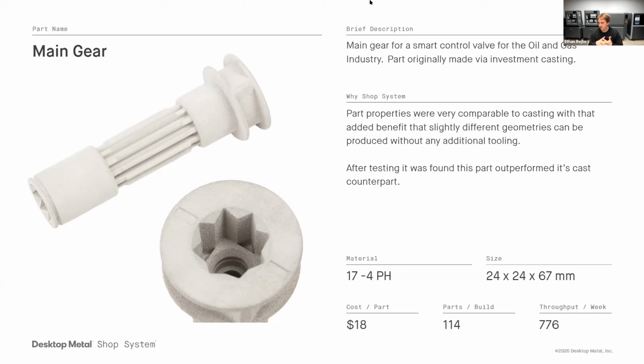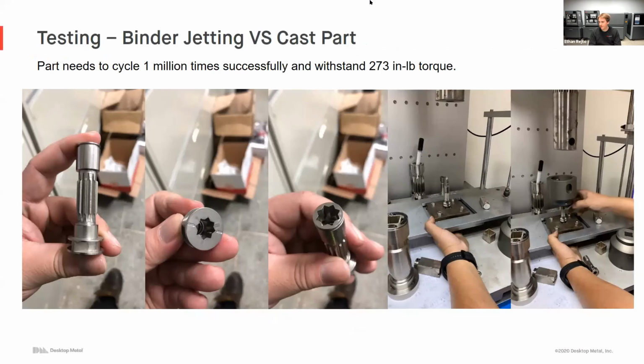This part was produced for just $18, and you can do over 114 of these parts per build, over 770 of these parts per week. When the customer went to test this binder jet part versus their cast original, the part needed to cycle 1 million times successfully and withstand over 270 inch-pounds of torque to ensure that it was adequate to be deployed into the field.